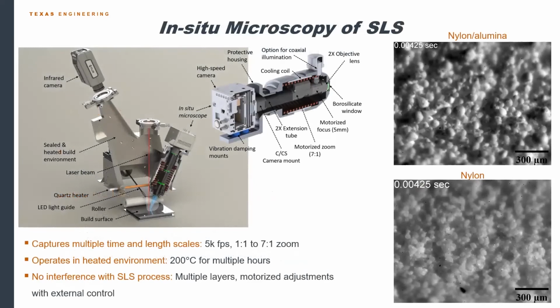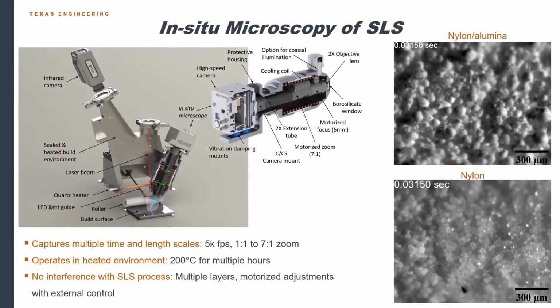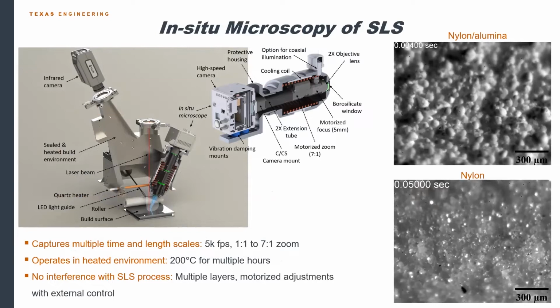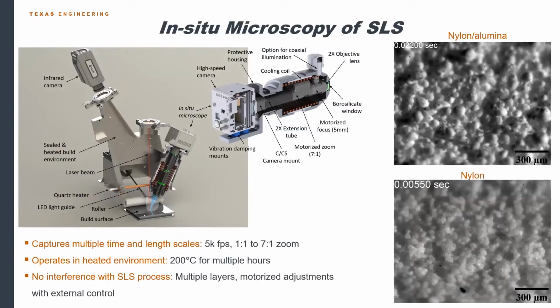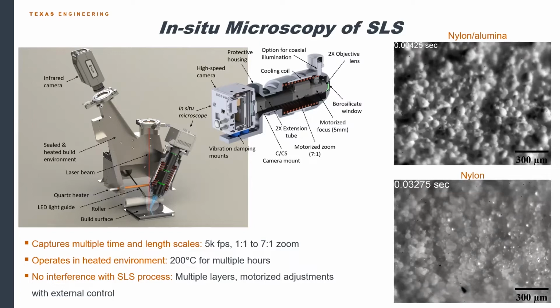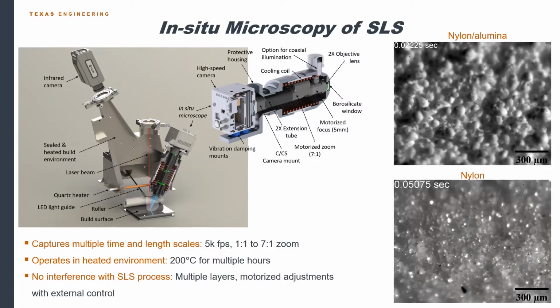I'll start with indirect selective laser sintering, and I'm going to highlight a new capability in our lab, which is an in situ microscope for the SLS process. We went into this work with ceramics thinking that the mixed ceramic and polymer powder behaved very similarly to nylon during laser sintering. So we designed this instrument and we actually proved ourselves wrong.